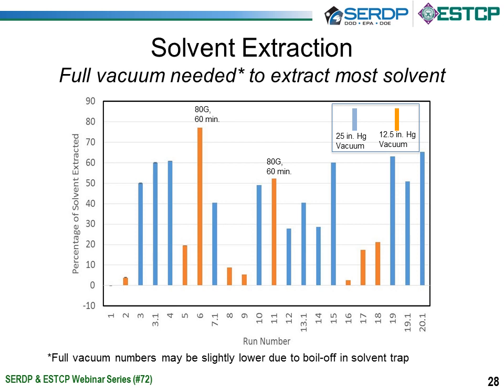But for the most part, with the half vacuum, we were only able to collect at most around 20 to 30% of the solvent. For the full vacuum runs, we were getting closer to 60 to 70%, but we believe that we were actually getting much higher solvent collection than that. Unfortunately, we did notice that the cold finger that we had was not an optimum cold finger, and we did see some boil off of the solvent going into the vacuum. So we believe that we were actually able to collect more than the 60 to 70% solvent as shown on the chart here.